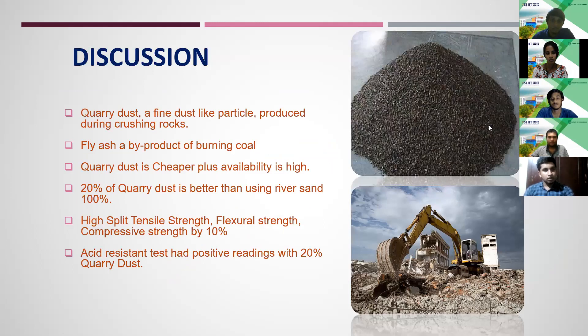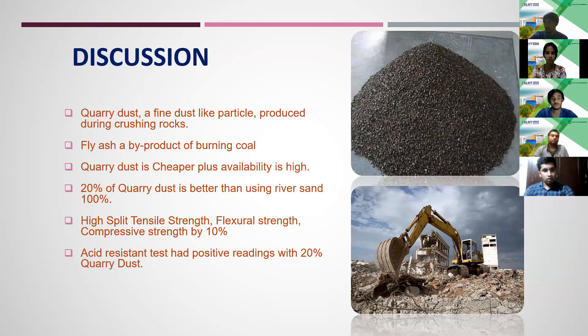Looking at the discussion: quarry dust is a fine dust-like particle produced during the crushing of rocks. At 20% quarry dust replacement, results are better than the control mix, with high tensile strength and compressive strength components improved by approximately 10%. Acid-resistant tests also show positive readings with 20% quarry dust.